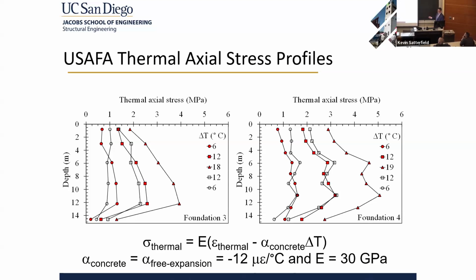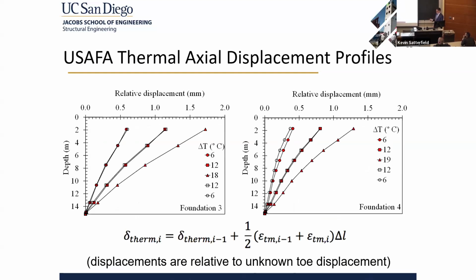That's more than the mechanical stress applied by the foundation. So that's something that we need to think about to make sure that those induced stresses are less than the capacity of the concrete. But the compressive strength of concrete is 20, so we're well below that. Assuming that the toe was fixed, which wasn't really the case, we could integrate the strains with depth and obtain the relative displacement. So we got somewhere around 1.5 millimeters of upward expansion during heating.